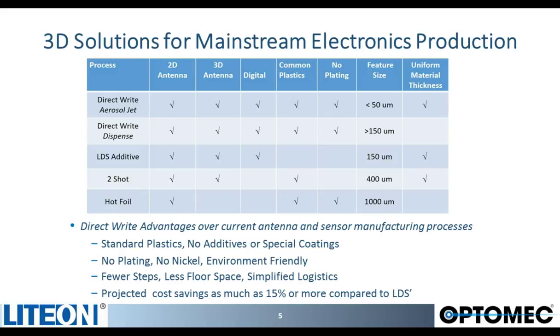When we look at aerosol jet prints directly on the surface of an injection molded part, which could be constructed out of standard materials such as polycarbonate or PC/ABS, so less expensive materials. Once the pattern has been printed with a conductive ink, it could be silver, it could be copper. It's then fully cured in an oven or using a laser to meet both mechanical and electrical requirements. The components are typically now ready for assembly. There's no need for plating or overplating steps, and the need for specialized plastics is eliminated. So some key advantages to the technology.